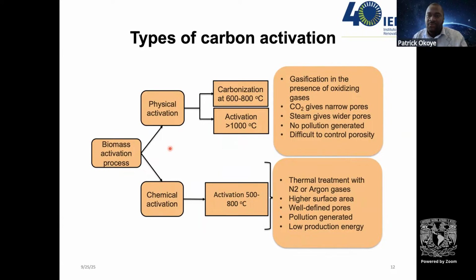So the challenge there is that during this washing, some pollution is generated. That is why, if you use several chemical agents like sodium hydroxide, zinc chloride, potassium hydroxide, sulfuric acid, phosphoric acid, be careful, because when you try to wash it off from the material after production, of course some of them will decompose, but there is excess in it. If you try to wash it off, you may generate more pollution. Hence, it is always ideal to use chemical agents that are far more environmentally friendly, like potassium carbonate.